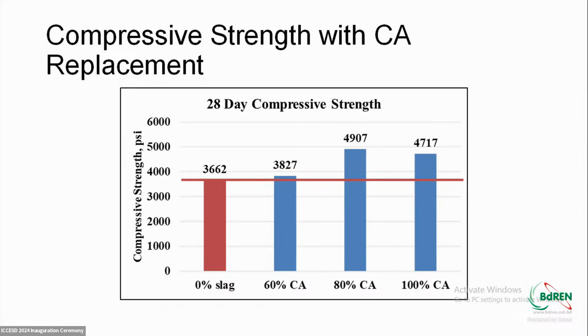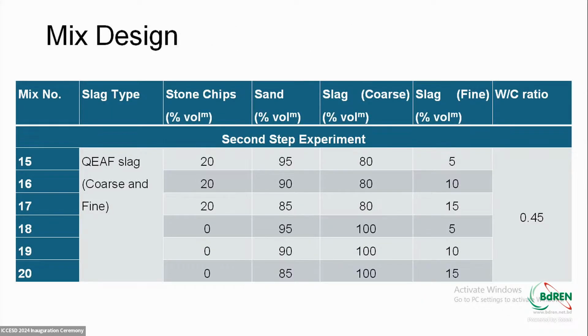In our second trial, after getting some experience, we used EAF slag, replacing both coarse aggregate and fine aggregate in different proportions—like 80% replacement of coarse aggregate and 5% replacement of fine aggregate, and so on, up to 100% replacement of coarse aggregate and 15% replacement of fine aggregate together.